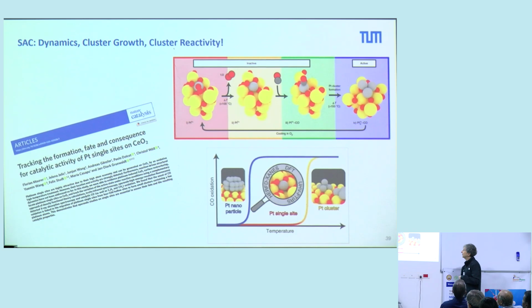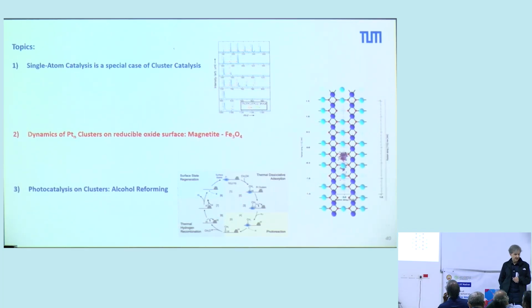And this dynamic behavior is also observed in real catalysis. These results are from the Grunwaldt group in Karlsruhe, and he showed that for the oxidation of CO on platinum on ceria, you have a dynamic change of the formation of atoms and clusters. If you are at oxygen-rich conditions, you are producing single atoms. If you are at CO-rich conditions, you are producing clusters. And he attributed the chemical reactivity of the CO oxidation to clusters and not to single atoms. And this is a very important behavior. So we learned that the dynamics of these clusters are important to somehow interpret the chemical properties.